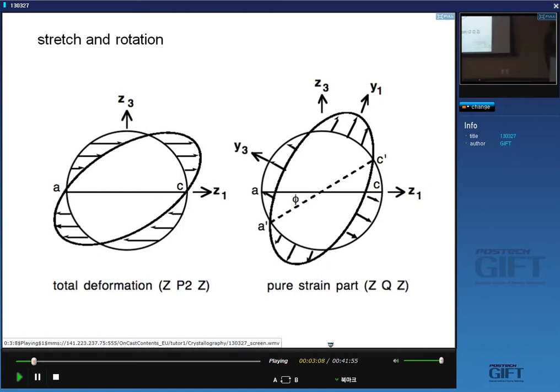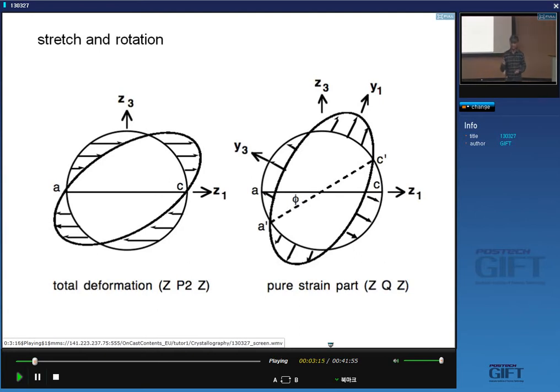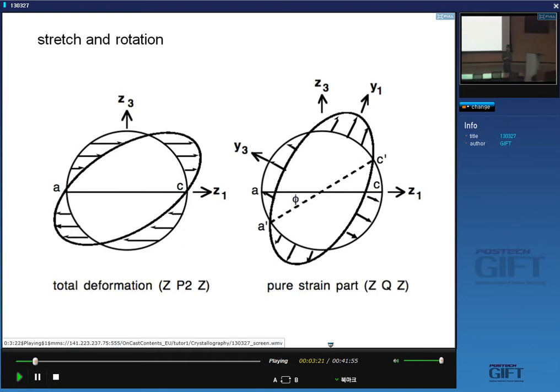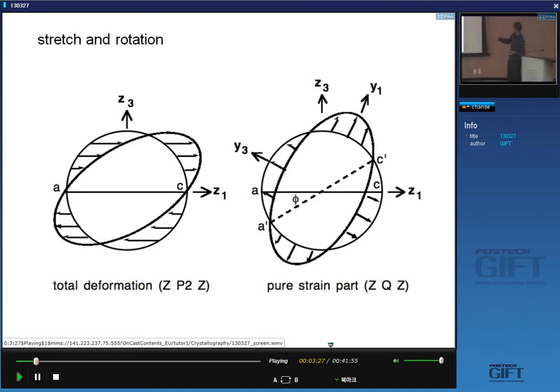In order to do this factorization, you need to express the deformation matrix in terms of its principal axes — those axes which remain unrotated during the deformation. They may be distorted. A rotation axis is not extended but remains pointing in the same direction. A principal axis of a deformation is unrotated but may be changed in length.